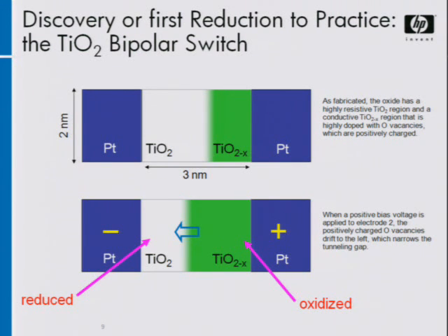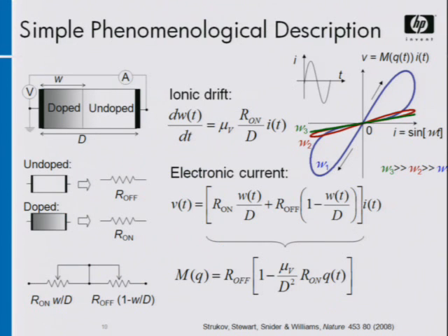And so that's really what was going on. If people had just thought about it for a minute, they would have realized that if it really is a capacitor, you don't have a pinched hysteresis loop, right? Your current voltage curve doesn't go through 0. It goes through something else. So all of these explanations for the effects that people had over 40 years were essentially all wrong.